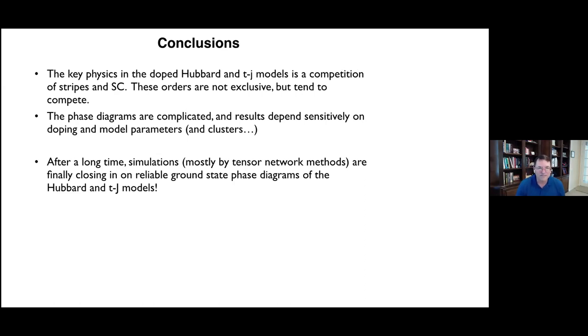Okay, just to give some overall conclusions: the key physics in the doped Hubbard and TJ models is a competition of stripes and superconductivity. These orders are not exclusive, but they tend to compete to a certain degree. They come from the same origin, so they're linked together. The phase diagrams are complicated, and the results depend sensitively on doping and model parameters, and of course computational details like exactly what size cluster or cylinder you're using. But the main conclusion is that after a long time, the simulations, mostly by tensor network methods, are finally closing in on reliable ground state phase diagrams of the Hubbard and TJ models.